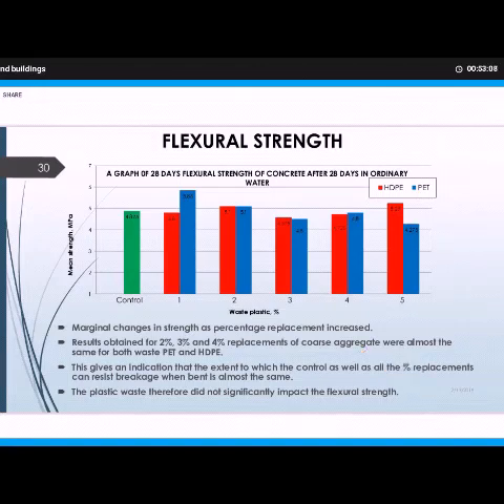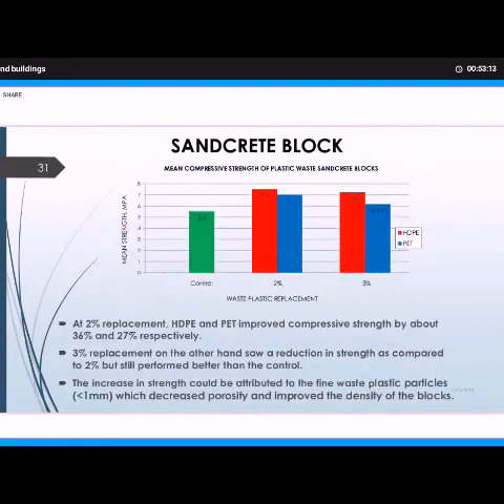So after the flexural strength, we also tried the waste plastic on ordinary blocks, because an ordinary person may not need to go into the lab to do any test. They have to just do it on the field. And when you go to the field, people do not use laboratory standards. So as much as possible, we try to replicate what happens on the field with the plastic waste. But now that you have already assessed it and you know that our optimum is around 3%, we decided to just work on 2 and 3% and not go beyond the 3%.